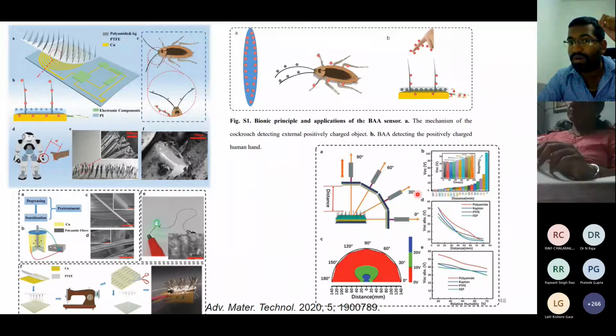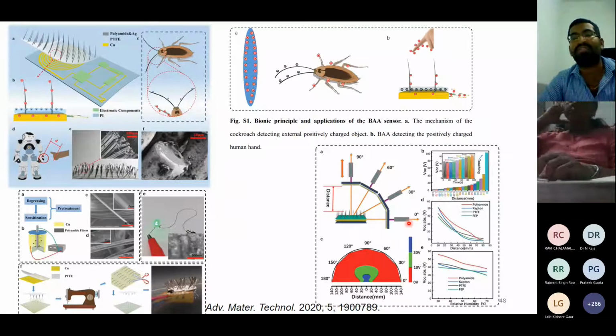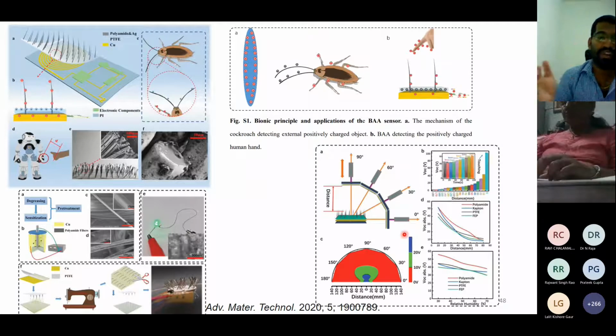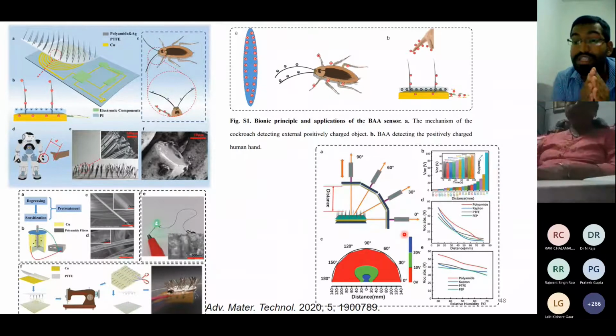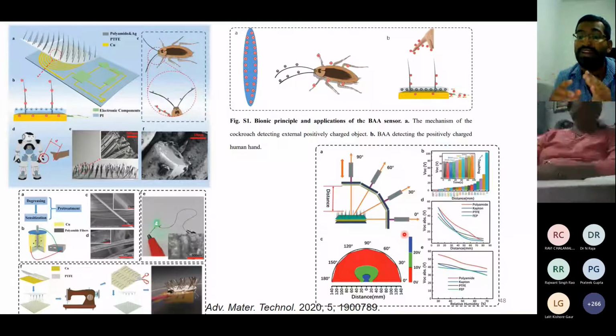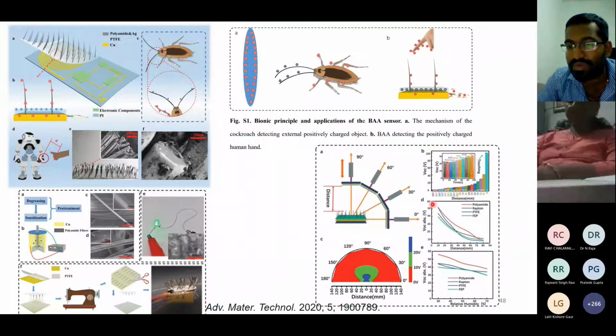Yeah, if you are using a comb, due to electrostatic induction, that's kind of the same mechanism, how it works, and how they can use this kind of technique for sensing your proximity. For example, if you are nearby or how far you are. So the distance can be easily calculated using this VOC, open circuit voltage. If your distance is too long, the voltage will be less. If you're getting very close and if you touch, the voltage will get high. And depending on the different distance and angle, you will end up with a different voltage response.